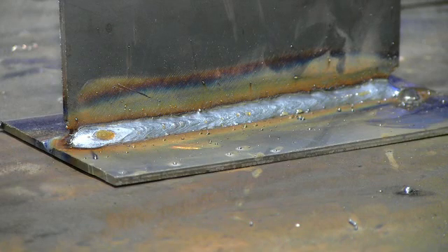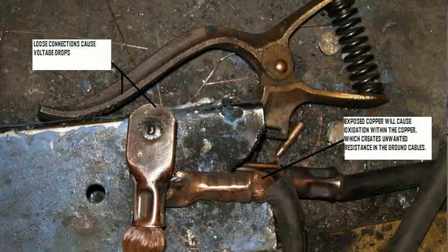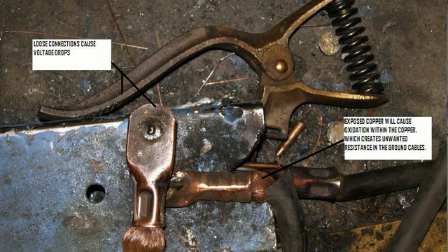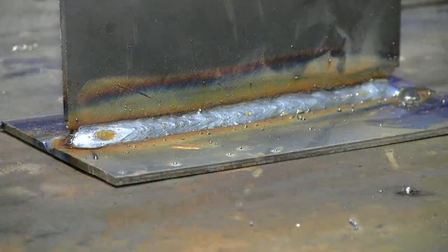And this can be caused by a couple things. Sometimes just the parameters are set wrong to a lower voltage, or there's voltage drops in the welding cables, which is most likely the cause of a spattery spray transfer weld. And the guy using the machine doesn't always know that he's got a voltage drop because he sets his machine to 27.5 volts, which should be good for spray transfer. However, he's got some terrible ground leads or welding cables, and he's got 2 or 3 volts of voltage drop, and so he'll never really get into a good spray transfer, and his welds will look like what you see right here.